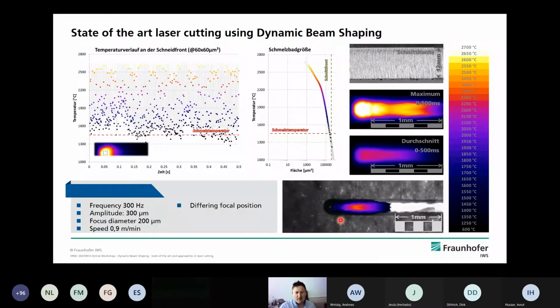Everybody knows that if we do this with standard cutting, we will get a worse cutting quality, so we call it a plasma cut. But if we superpose this dynamic beam shaping, in this case using a frequency of 300 Hertz and an amplitude of 300 micron, we can achieve quite good quality. And if you look here, also at a quite high process speed. So we could increase the speed from 0.5 to nearly 1 meter per minute.